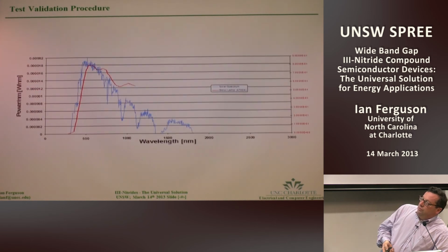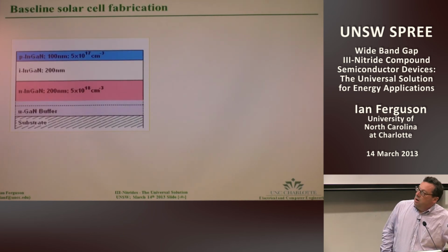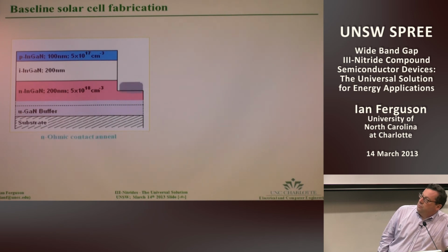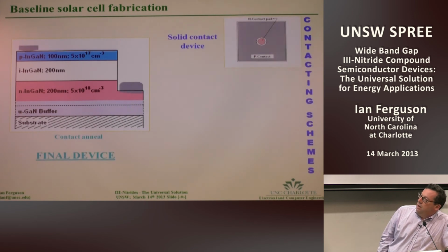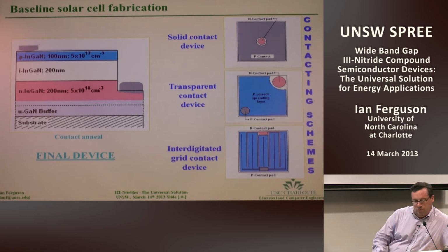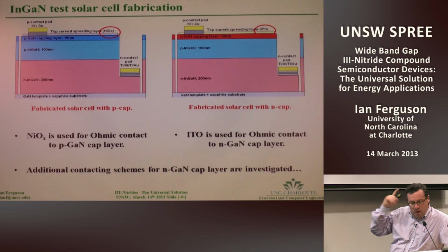And the other issue we had with these wide band gap materials, we used Solux lamps and other things, was because you're in this region where the power spectrum is dropping, a slight difference in the color temperature of the lamp or how you drive it can make a big difference in the efficiency of the solar cell. So we made different types of devices, both with transparent contacts, semi-transparent contacts, finger contacts. Again, I don't have enough time to show interdigitated and also recessed contacts we started doing as well. I won't show it here.